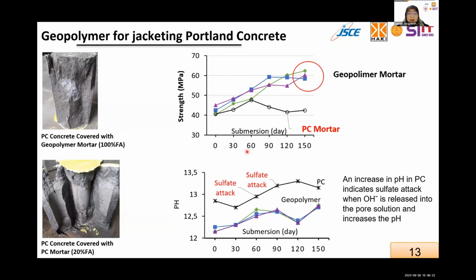This is the result when the wrapped concrete was immersed in seawater, and we compare with the jacketing made with PC mortar. The decrease of the strength in wrapped concrete with PC is shown here. However, wrapping with geopolymer mortar shows better mechanical properties. Maybe the sulfate already attacked the PC wrapping. In the system, the pH increases, showing that the release of hydroxyl ions is a sign of the decomposition of the calcium silicate hydrate.